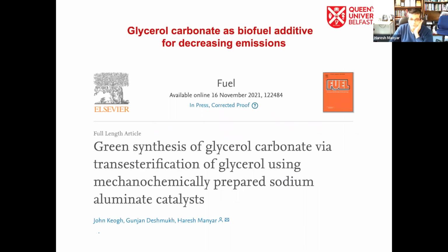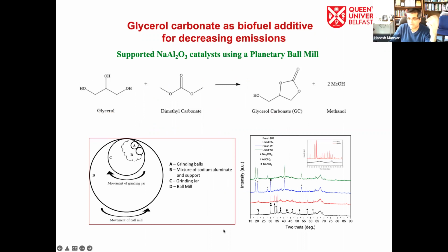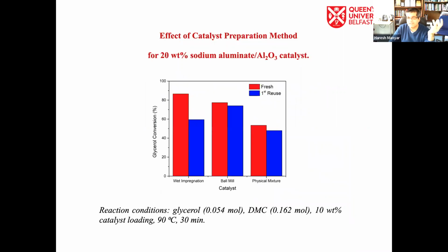Looking at that, the study which we did was green synthesis of glycerol carbonate by mechanochemically prepared materials. In this case, we used ball milling. We prepared our catalyst by milling. Sodium aluminate type catalysts were used by incorporating them on alumina. Again, earth abundant metal oxides, easily available in bulk and can be scaled up very easily, with very nice catalytic performance. Compared to wet impregnated materials or physical mixtures, the ball milled materials were much more stable. The recyclability study showed that the efficiency of the materials could be improved by using mechanochemical grinding instead of wet impregnation. I'll come to that in a minute.